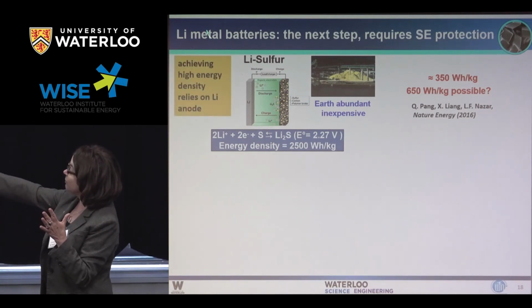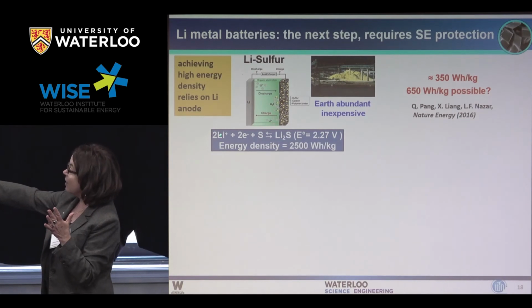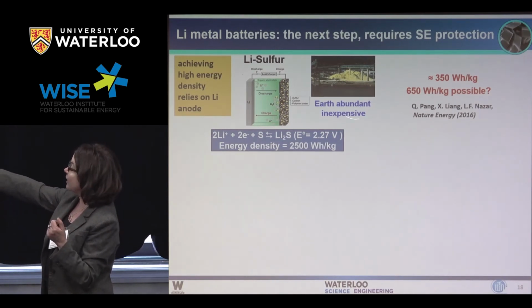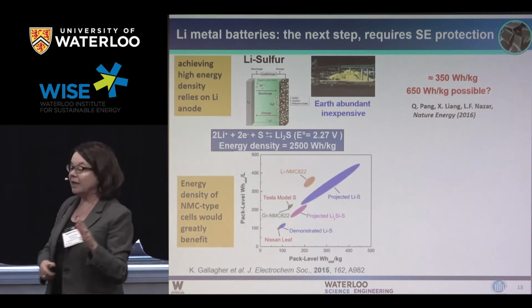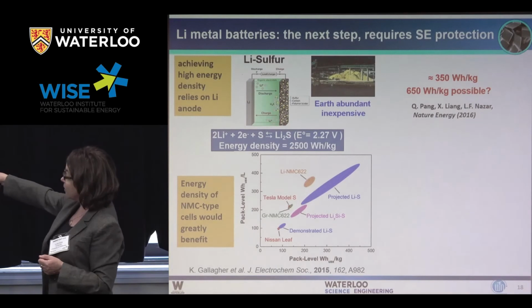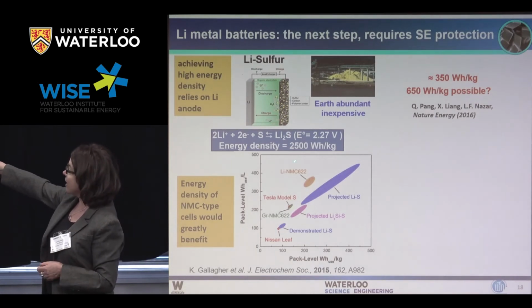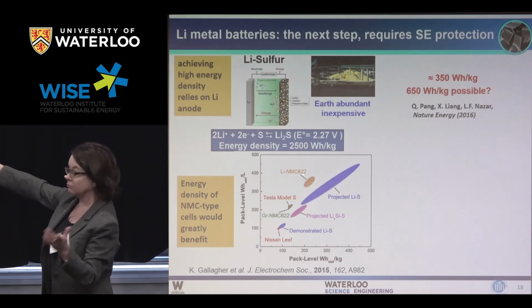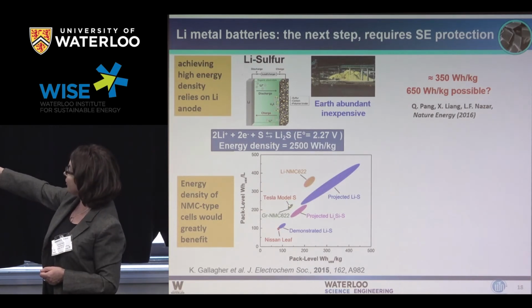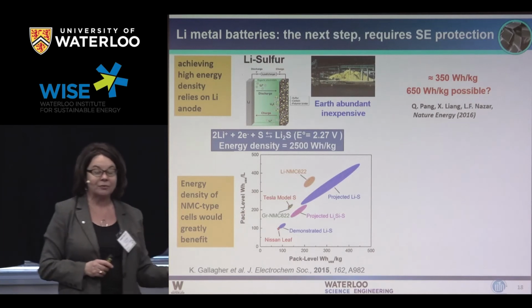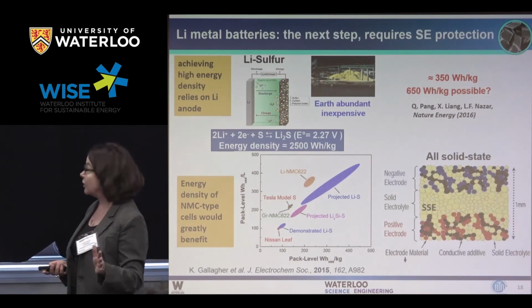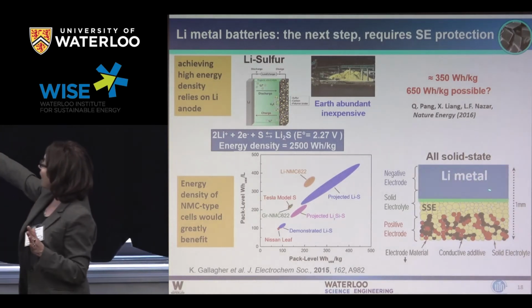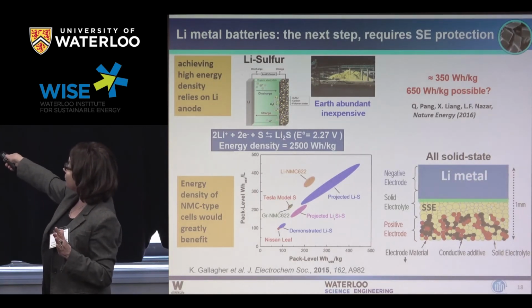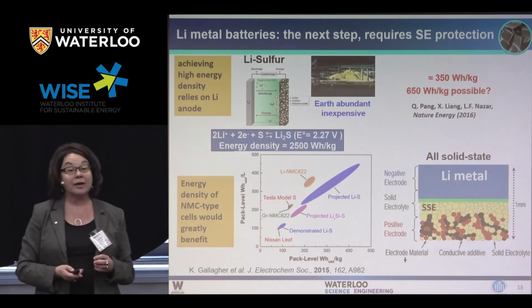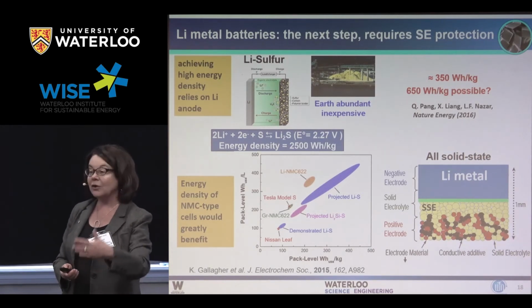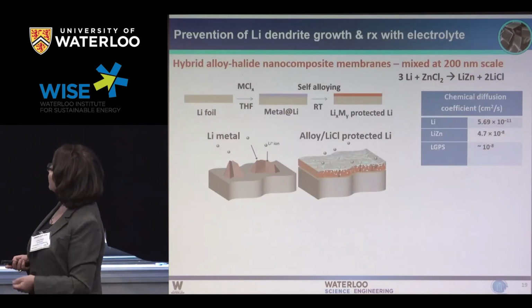And one of the places we want to advance it is for lithium-sulfur batteries because they rely on having a lithium negative electrode and a really inexpensive positive electrode. But even if we don't consider sulfur batteries, if we put a lithium metal anode or negative electrode in the normal type of cells that we're using in the Tesla, we would go from an energy density to here all the way up to here, simply by swapping out the negative electrode. So as I said, this is a huge push, and that means that we have to develop protective membranes and interfaces to the rest of the cell. And that's kind of what I would see as the next big push, and as I said, I can tell you that with great confidence because everyone in our community is working on this.